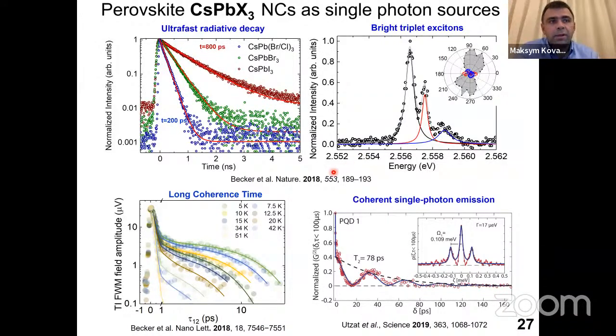And what was also extremely exciting, and this is essential for the future, is that they can retain at low temperatures their exciton coherence for a decent fraction of their radiative lifetime. And so basically they are reasonably coherent emitters at the single photon level. And this motivates to build collective states where potentially these single emitters might couple into larger aggregate states with coherent emission as a collective state. And so one way to design such aggregate states would be to self-assemble quantum dots into superstructures.